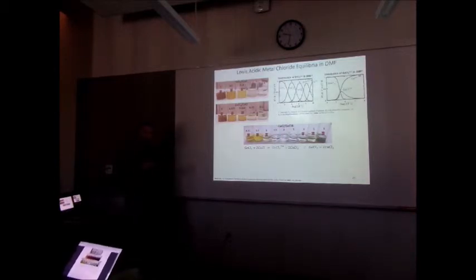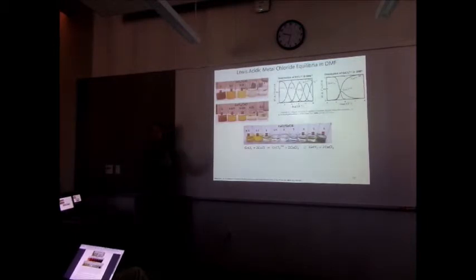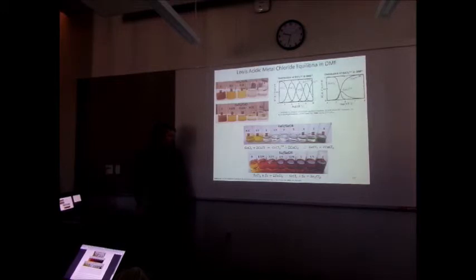So I was able to find that these equilibria exist for indium chloride and gallium chloride between these different chloride complexes in DMF. I also had put together how germanium chloride is stabilized as well in kind of the reverse mechanism as copper chloride. Copper chloride is stabilized by accepting chloride in solution, while germanium chloride is stabilized by giving away chloride. And this is really fortuitous because they happen to stabilize each other in the exact range we need for this alloying strategy that I'm working towards. Additionally, another interesting result we found is we were able to stabilize these selenium chloride complexes and stabilize selenium directly through the formation of these selenium polyselenides in solution.